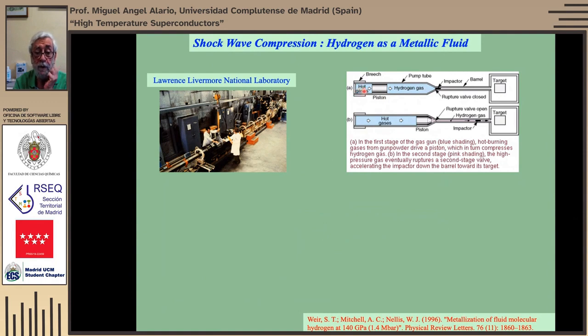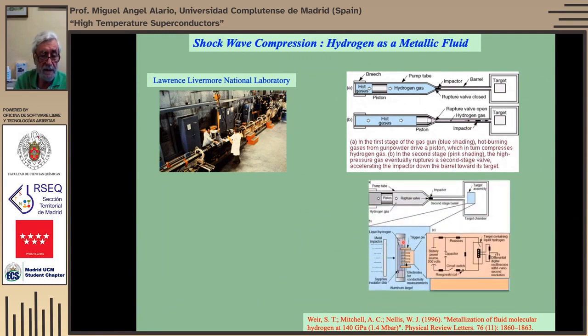So when you ignite this, there's an explosion, and the piston compresses the gas in here, and then you have here an impactor, and the impactor runs along the barrel of the gun to the target. At the beginning it is like this, then the hot gases push. And that's the target. The target is in fact composed of two alumina crystals, and we have hydrogen in between. And then you have a series of connections to measure the resistivity. So this impactor is the one that actually touches here at very, very high speed.